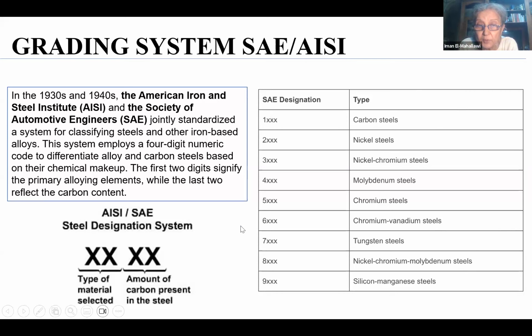Usually the first number from 1 to 9 would refer to the type of the steel. And then you have 4 digits, where the last 2 refer to the percentage of the carbon, and the second one after the first would describe the other alloying contents in the steel. Usually the grade 1 would be the carbon steels, 2 would be the nickel steels, 3 would be the nickel chromium, 4, which is very well known and common in the market, are the molybdenum steels, and then we have the chromium steels 5, 6 are the chromium vanadium steels, 7 are the tungsten steels, 8 are the nickel chromium molybdenum steels, and 9 are the silicon manganese steels.